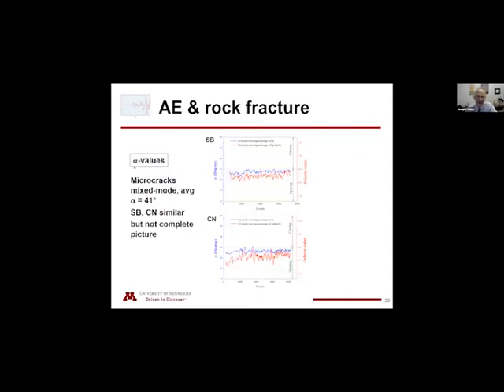Okay, the alpha values. This is a mode 1 fracture test, and these alpha values are shear dominant. So I didn't say it, but if alpha is equal to 45, that's a shear crack locally, and we have an average value of 41. We also use a polarity method to check against the crack model that we're using, and it gives us similar results. But it's not the complete picture because this is local. So of course the crack has some orientation, and if that orientation is not vertical in terms of how we are setting up our specimen, then just considering that opening is in the X direction, there must be some tangential component. So at least that's how we explain this dominant shear behavior.